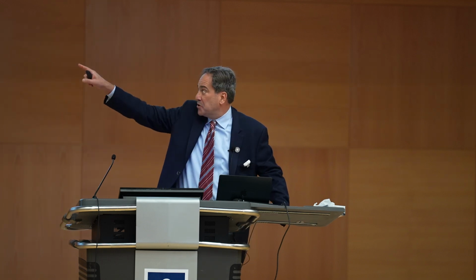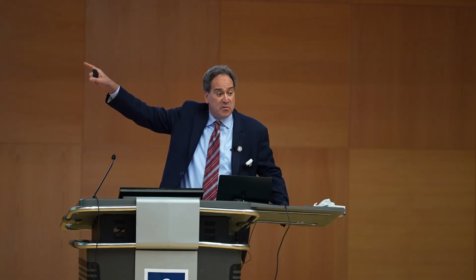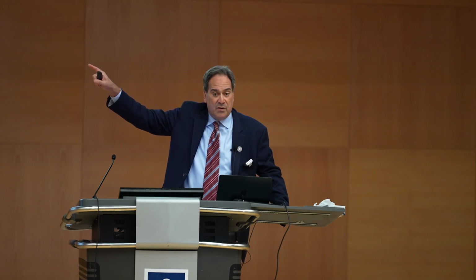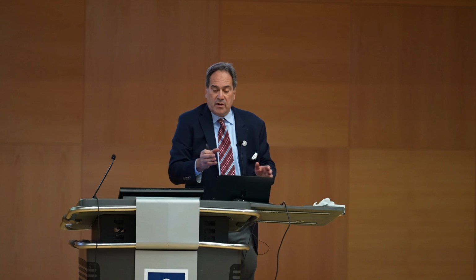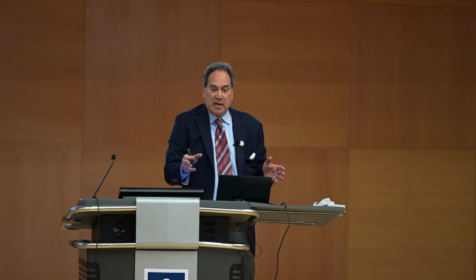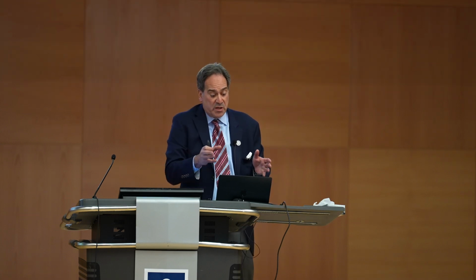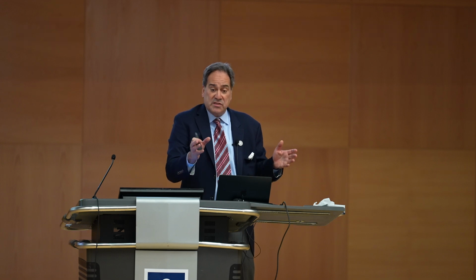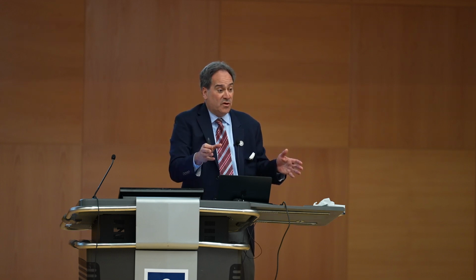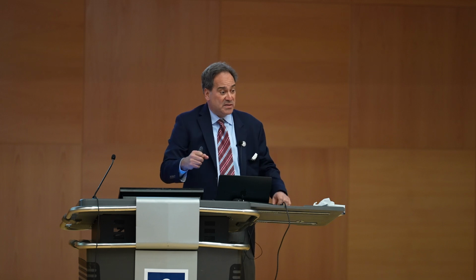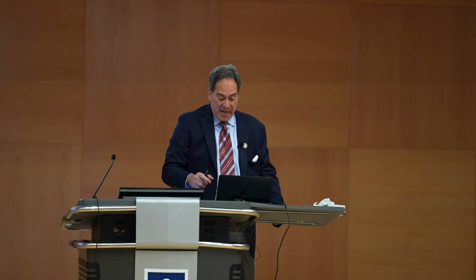And you can see platinum's pretty high, but it's not the highest. There's some 3-component systems that he modeled that we had made that are even higher. Well, we can make those, and so this gives you a feel for how we can begin to design catalysts based upon these types of tools, because we can go to the lab, we can make these compositions on a glassy carbon electrode, make them in mass, and then drive them and look at how they compare to platinum.